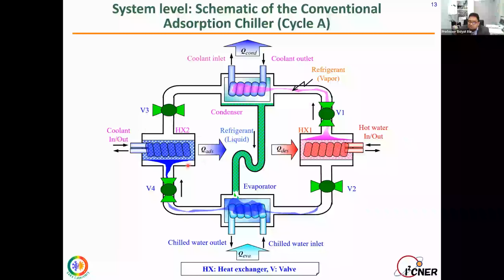So one pair is in adsorption mode, the other is in desorption mode, and then vapor goes through valve 1 to the condenser. The condenser is also a water-cooled condenser. So we are cooling down this vapor, and the phase changes in this condenser, and the liquefied water again comes to the evaporator. The science here is that when water evaporates, it creates a temperature difference. For example, water inlet is about 12 degrees and the outlet would be about 7 degrees. Then the temperature difference can be used as the cooling energy. If you have more water inlet flow rate, you have more cooling energy. Of course, it depends on the size of the system.